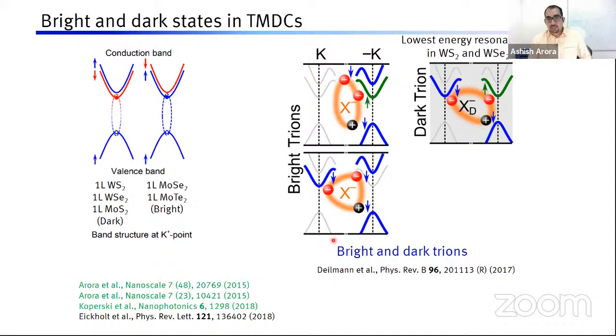I will not go into details because this is a bit involved. However, we can create another type of trion where this hole is of the opposite spin than the electron. Then you can have another electron here in the other valley, and this trion is a dark trion, because the exciton here is dark. The exciton decides the selection rules. Now, this would be the lowest energy state, and it should contain most of the carriers at low temperature.